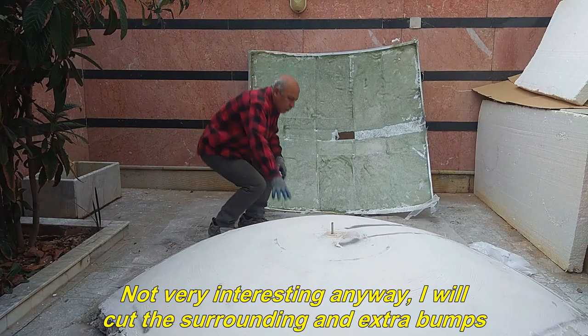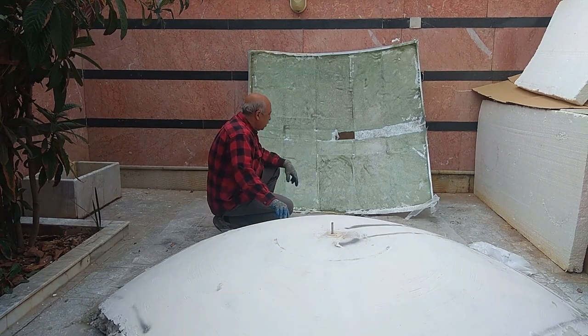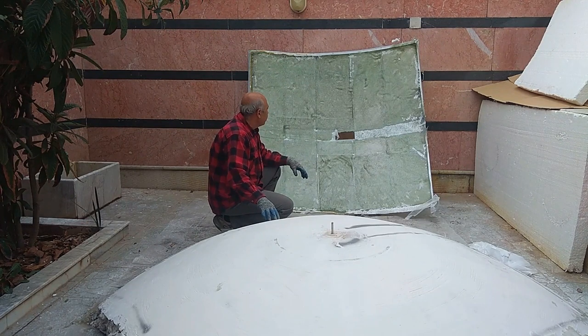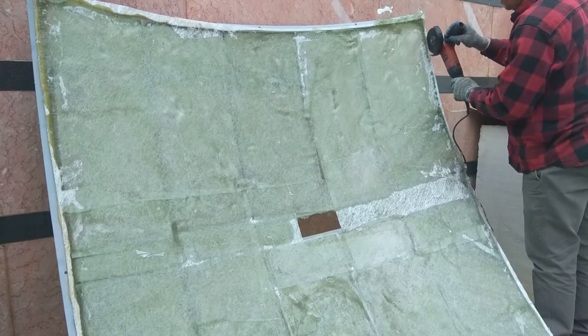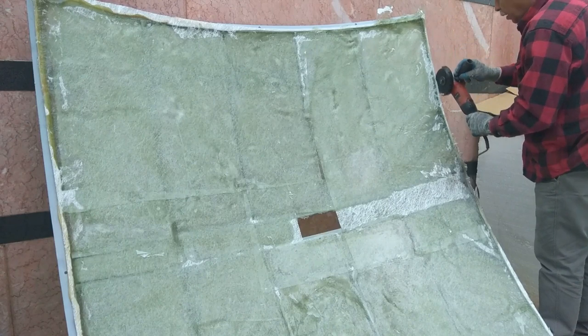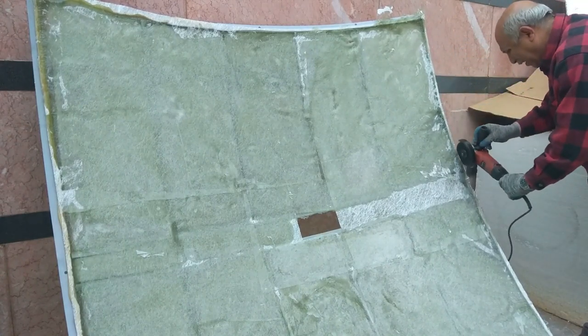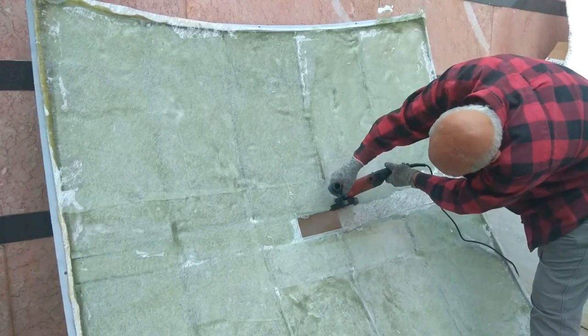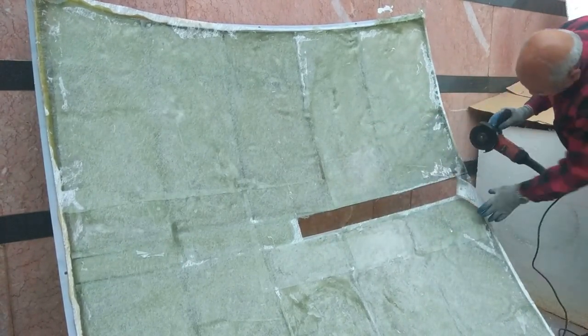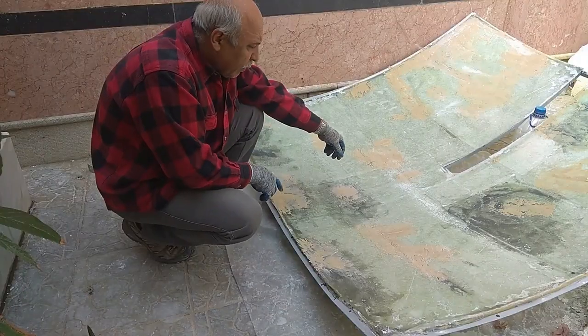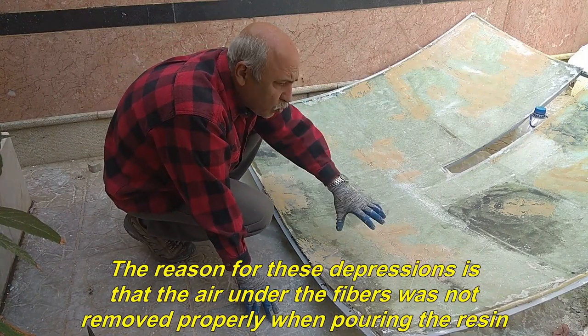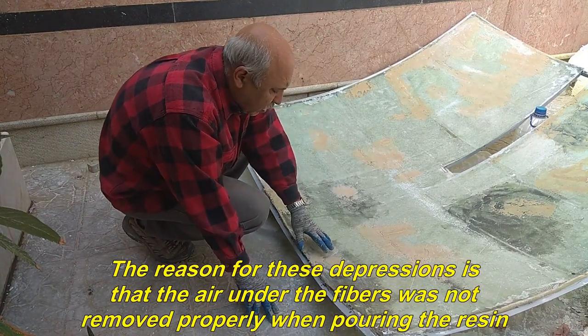Not very interesting anyway, I will cut the surrounding and extra bumps. You can see that the work surface has a depression and we have to putty its surface. The reason for these depressions is that the air under the fibers was not removed properly when pouring the resin.